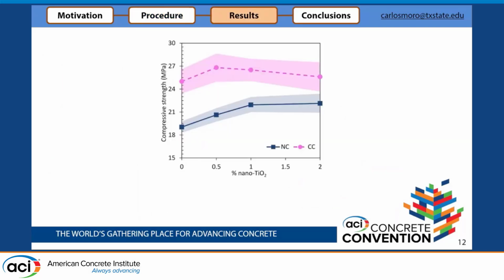Here I show compressive strength with the 2 different curing methods, compressive strength on the y-axis and percentage of nanotitanium dioxide on the x-axis. If we follow the blue line, that is the normal curing, or moist curing, or conventional curing, we can see that increasing the percentage of nanotitanium dioxide is beneficial to improve the compressive strength, right? We already saw that in the literature, but the interesting part is that in the CO2-cured samples, the optimal percentage of nanotitanium dioxide is lower, right? Now the maximum value that we have is at 0.5%. So the question is, why is it lower than in the normally cured samples?